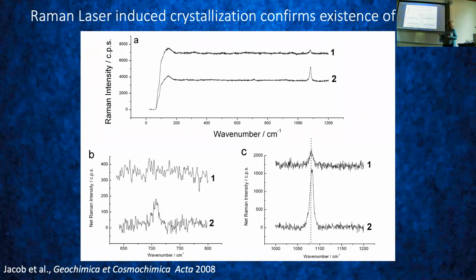You can do tests. We found areas that are amorphous, because we wanted to know, is that really amorphous calcium carbonate, or is that maybe just organics, which are often amorphous? So we found areas in pearls and shells that were amorphous, judging from the Raman signal. Normally you would get really peaky patterns. With amorphous material, you only get flat curves. There was a little peak here, which could have been the carbonate peak. And to test whether we are really measuring organics or mineral, we just left the laser on for a while.